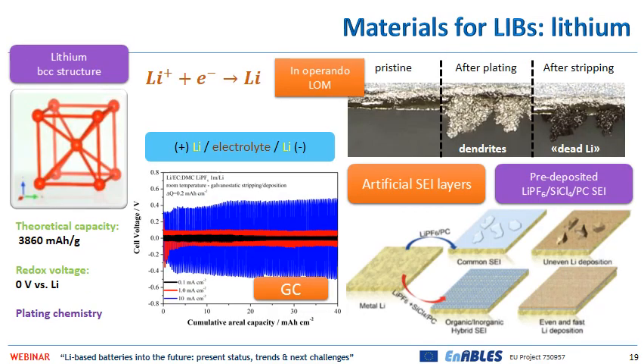Another very good material for lithium-ion batteries is lithium. It's another negative electrode material. Obviously, the formation and the redox reaction of lithium is very different from the two that we have tackled before. First of all, the very good news of this material is the excellent theoretical capacity. The way in which this material operates in lithium cells is through the so-called plating-stripping chemistry, meaning that we have the nucleation of new particles of metallic lithium during discharge and dissolution of these particles of lithium during charge.